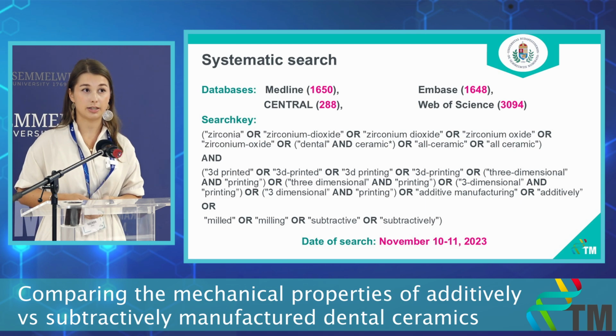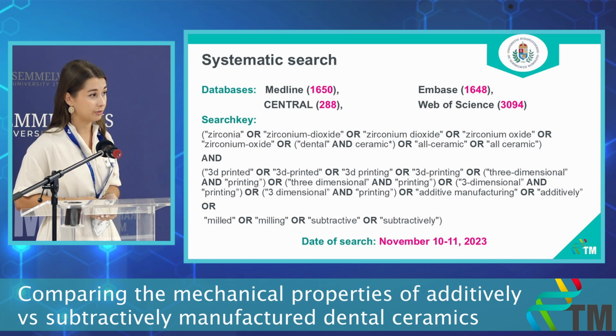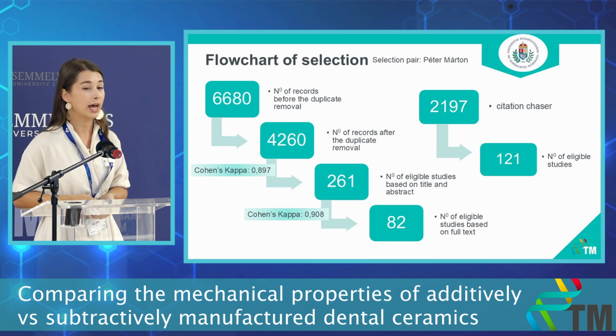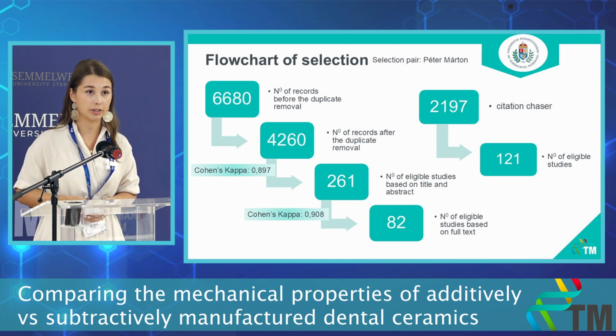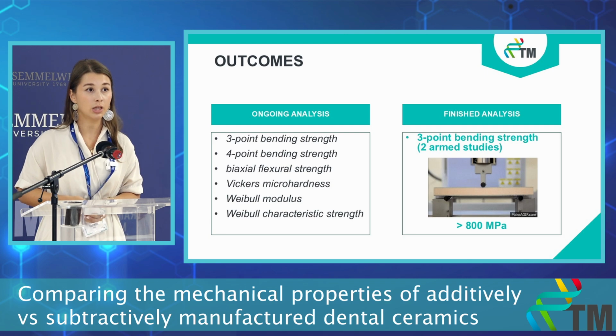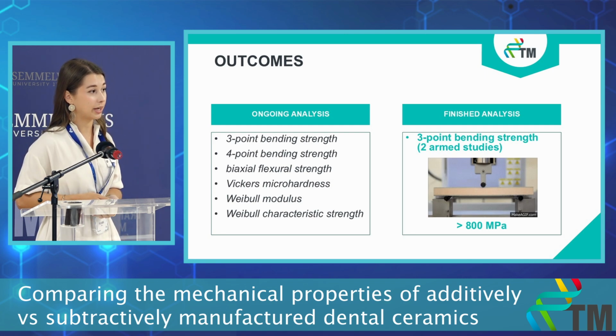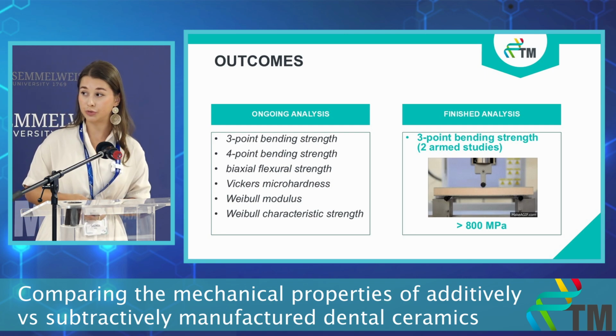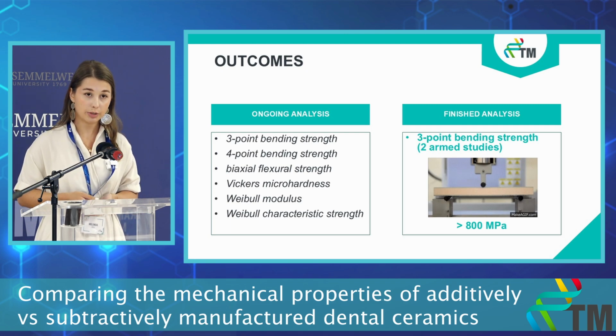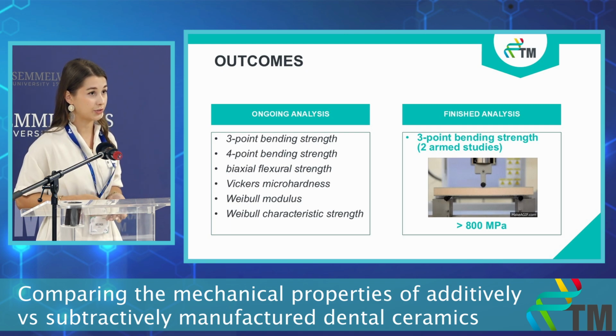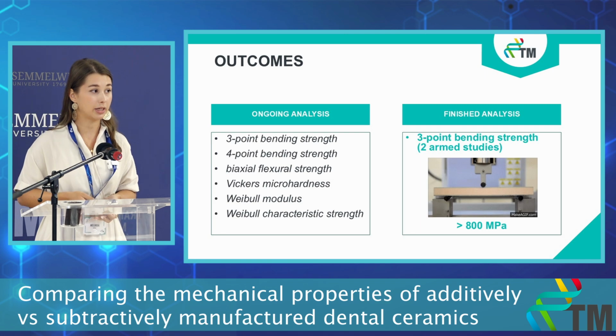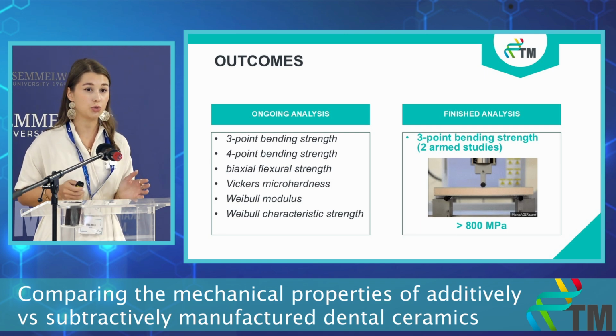Here you can see the details of my systematic search that I conducted in 4 databases, and after the selection process, I ended up with 203 included articles. On the upcoming slides, I would like to show you our partial results for 3-point bending strength. So 3-point bending strength is flexural strength measured with 3-point bending test. The unit is megapascals, and for zirconia, it ranges usually above 800 megapascals.